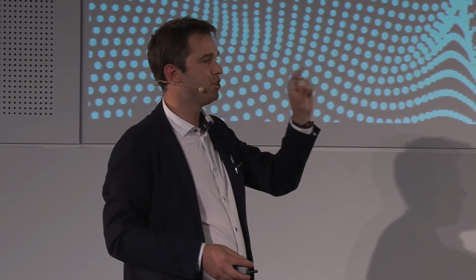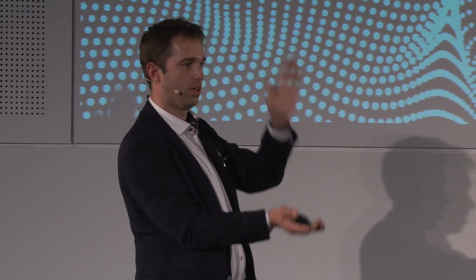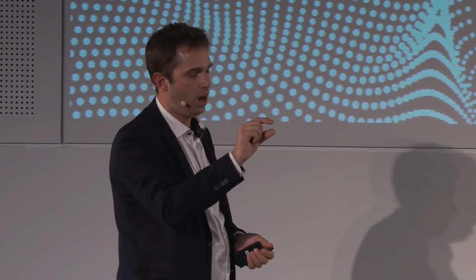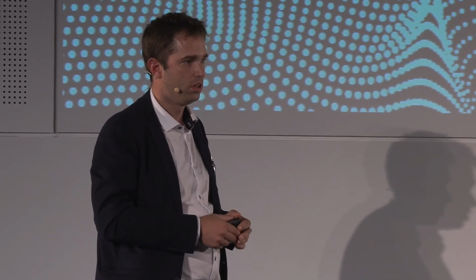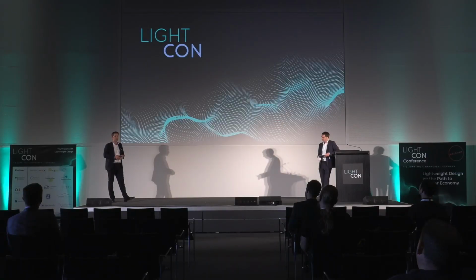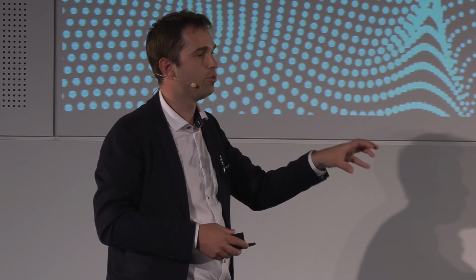So in terms of impact area, as long as you do not go above a certain thickness, then it's fine. But it's more on the side of thickness of the damage. So if you have two layers that are open, like a mode 1 DCB test, you know, this will not work, of course. But as long as you stay really with small delaminations in the order of 100 microns, then this will work. And this is the start, and this is what we have always seen, that these are the small damages that will grow until catastrophic failure. And we really want to act at the beginning of this damage problem, let's say.